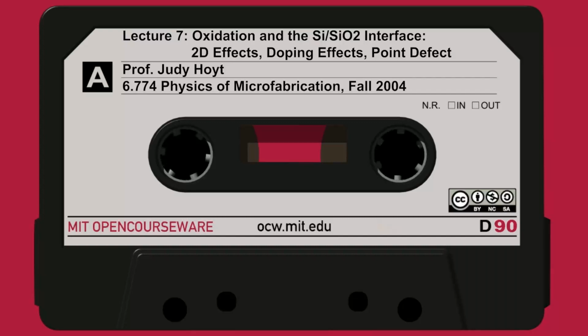We talked about stress. So there's an oxidation reaction happening right here at the borderline between the pink and the white region, here at the star. They can consume vacancies or they can generate interstitials. So I've got a vacancy going in, interstitial going out, either way, in order to provide the volume needed for the reaction. So we need room to put these oxygen atoms at that interface. And that room comes from vacancies and also kicking out silicon atoms from the lattice, creating interstitials.